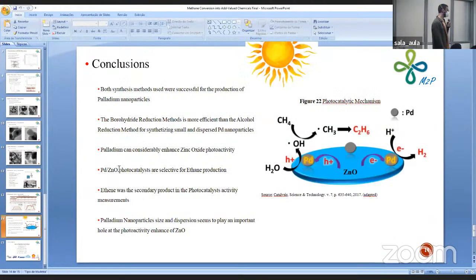So as conclusions, both synthesis methods were successful for palladium nanoparticle production. The borohydride method is more efficient than the alcohol reduction method at producing dispersed and smaller nanoparticles. And this palladium seems to enhance the zinc oxide photoactivity, having ethane as main product and ethene as secondary product. And we can see that the size and dispersion of the particles might play an important role in the conversion of methane in this photocatalyst.